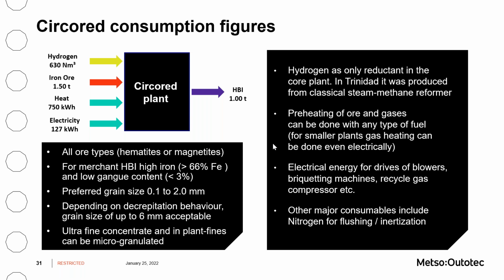The preferred grain size should be in the range of 100 micron up to 2 millimeters. If substantially finer, microgranulation can be applied. For coarser material, size reduction is needed. Hydrogen is the only reductant in the process, regardless of its origin. For preheating, any fuel can be used. Future process variants will be fully electrified. Nitrogen for purging and inertization is a consumable and needs to be considered in the balance of plant.